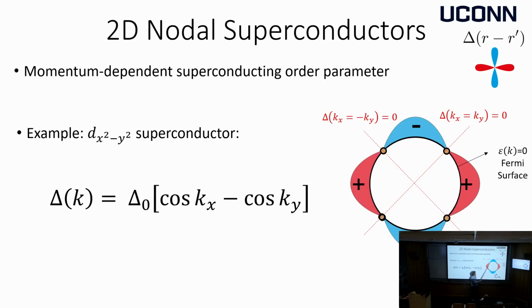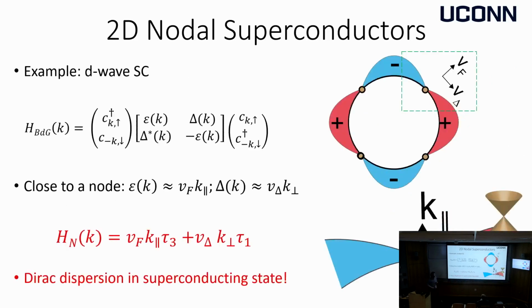And specifically, as it changes sign, there will be particular points on the Fermi surface where the gap closes. And if you really work this out, taking the dispersion of electrons, the dispersion of holes, and the pairing between the two by the superconducting order, you find before long that expanding around those points, the Bogoliubov-de Gennes Hamiltonian, the low energy quasiparticles behave as Dirac fermions. So that gave essentially some initial impetus for us to work on this problem, because we have layers that have Dirac fermions. These Dirac fermions are not electrons. They're some kind of superpositions of electrons and holes, but they're Dirac fermions, and we can twist them, and maybe we can play the same game that people played with twisted bilayer graphene.